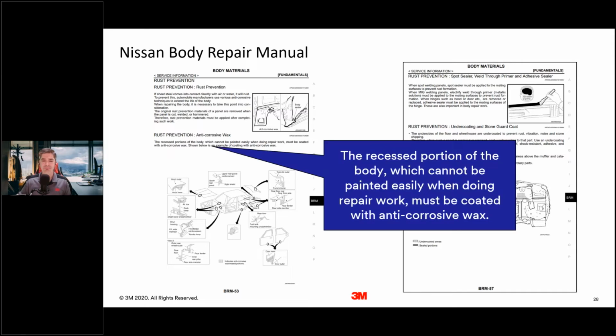But going back to Nissan, I want to talk about when we're referencing cavity wax, areas that can't be coated, accessed with a paint gun. We don't want to be blindly spraying primers and coatings into cavities, like in rocker panels, in sail panels. These coatings may not cure properly. They may take longer than needed. And if they pool up in those pinch weld areas, they could become very brittle and actually shrink and open.